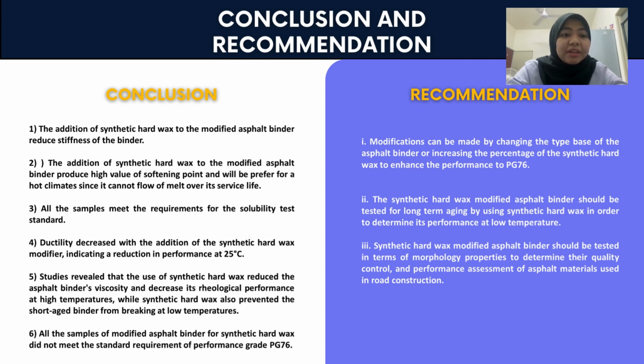Lastly, all the samples of modified asphalt binder with synthetic hard wax did not meet the standard requirement of performance grade PG76. These are the project recommendations for the future. First, modification can be made by changing the base type of the asphalt binder or increasing the percentage of synthetic hard wax to enhance the performance to PG76.